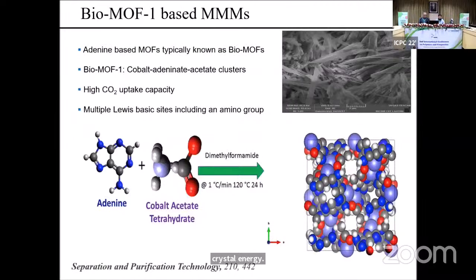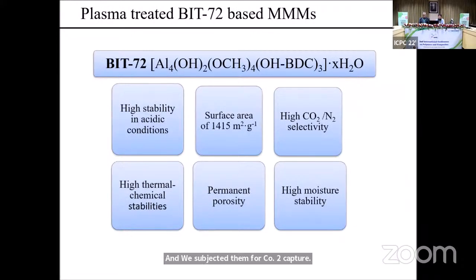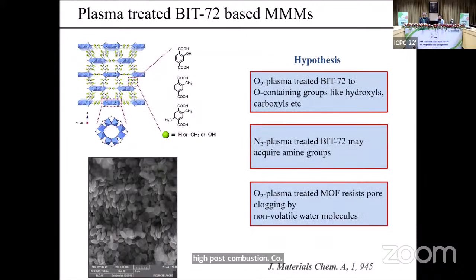and we subjected them to CO2 capture. Finally, the last material that I will talk about is BIT72 based MOF. It is a highly stable aluminum based MOF with a surface area of more than 1000 meters square per gram, and this material has also shown very high post combustion CO2 capture properties. What we did was we collaborated with the University of Liverpool with Professor Shintu's group, and we carried out post modification using oxygen and nitrogen plasma to induce oxygen and nitrogen based functional groups to enhance CO2 capture properties, and we were able to obtain very nice pebble shaped MOFs.